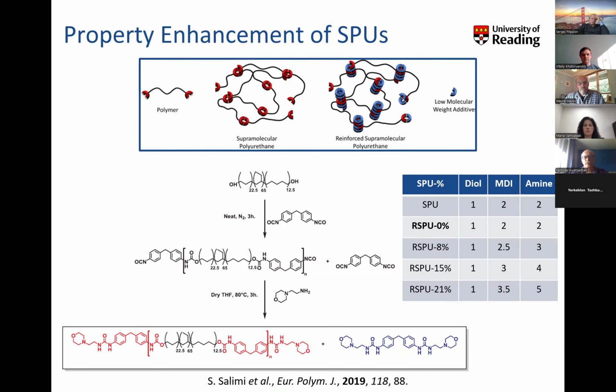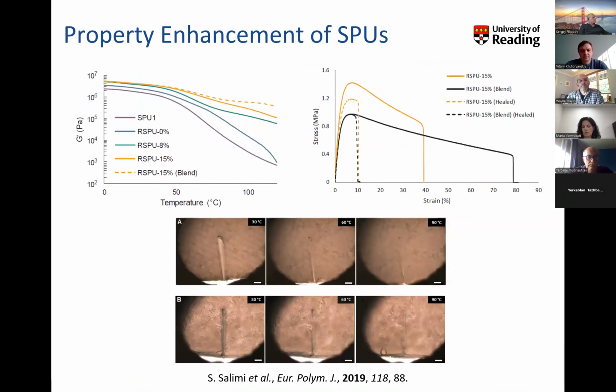But one of my PhD students didn't do that. She simply took the raw material and studied it. And she varied the monomer feed such that we could adjust the loading of that relatively low molecular weight component. And so what we were trying to do was to see if these low molecular weight components would enhance the phase separation and reinforce the supramolecular polyurethane. Well, obviously they did, otherwise I wouldn't be telling you that.